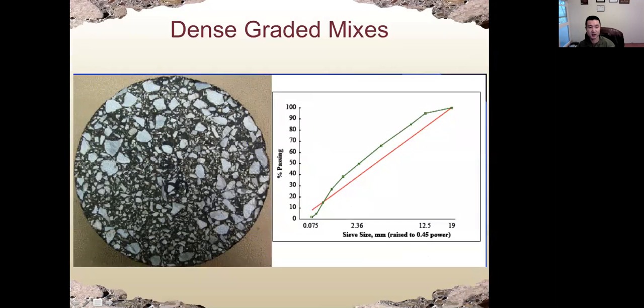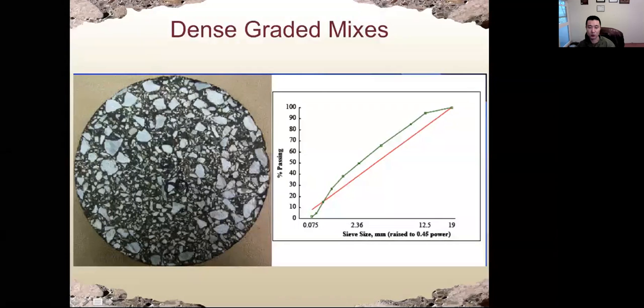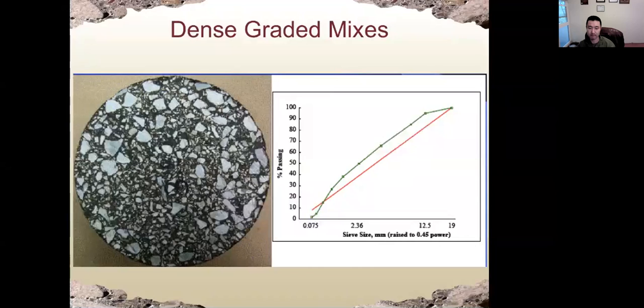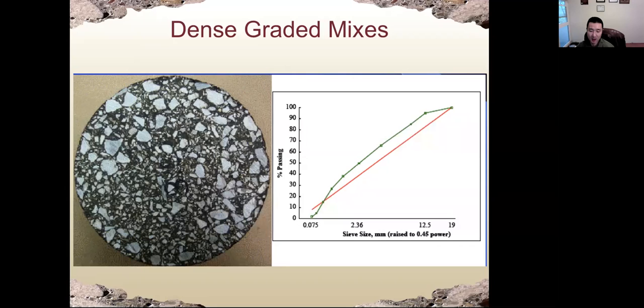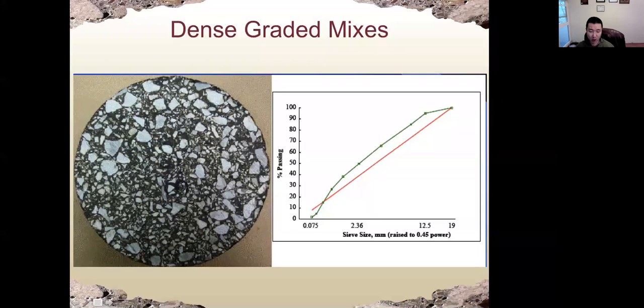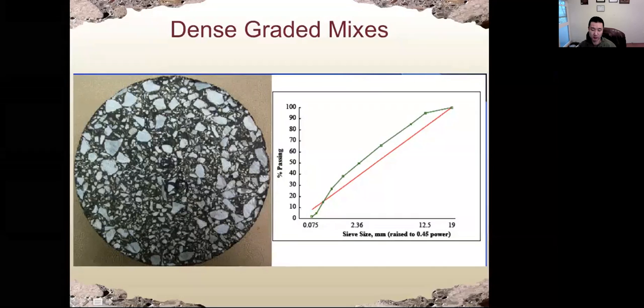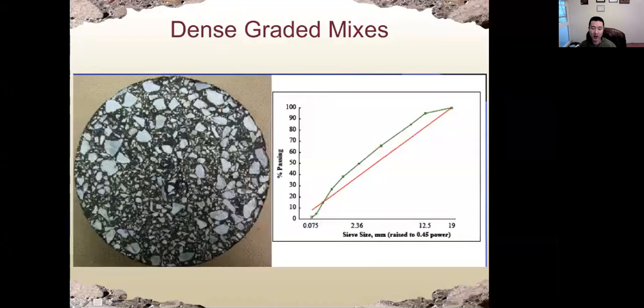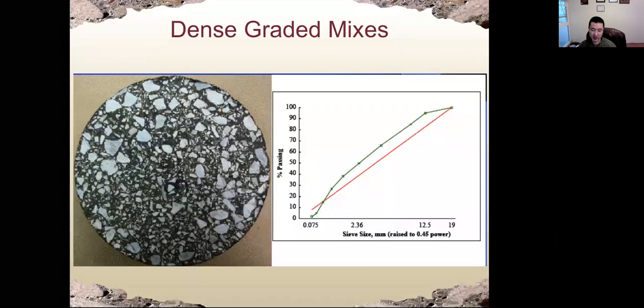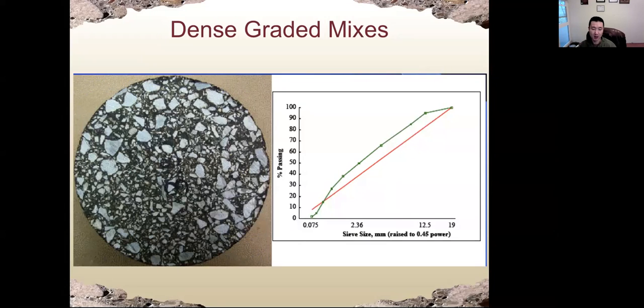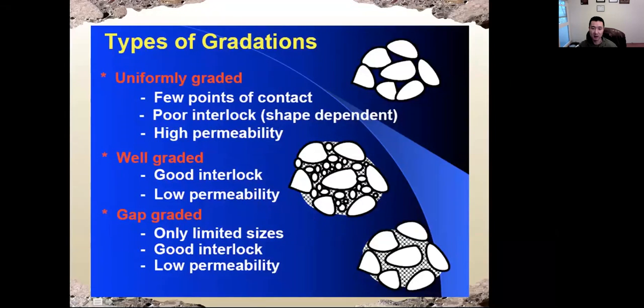All right. So this is the cross section of asphalt concrete with dense graded. Okay, we call that dense graded mix. For the dense graded, the sand is in control. So the sand will carry most of the load. For coarse aggregate, there is not too much coarse aggregate in the system. So there's no interaction or no particle-to-particle contact between coarse aggregate. So sand will take most of the load. So this is called dense graded mixes. This belongs to the second category, the well-graded mixes. It has coarse, intermediate, and small aggregate.